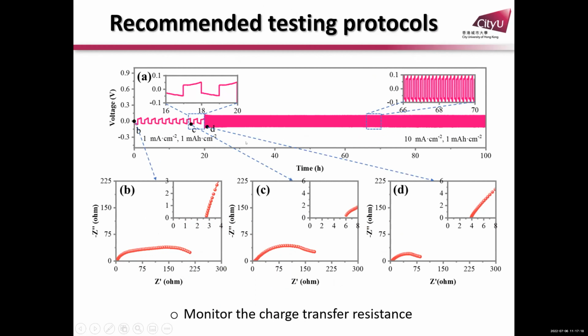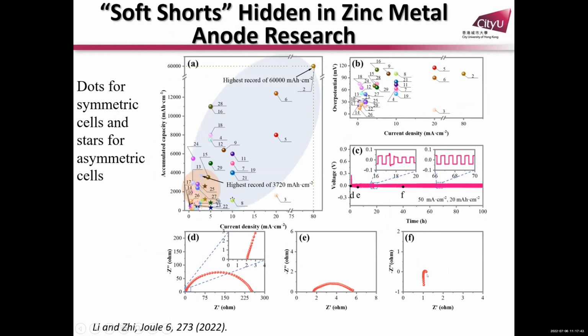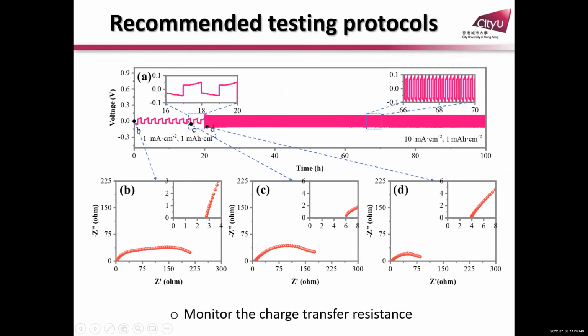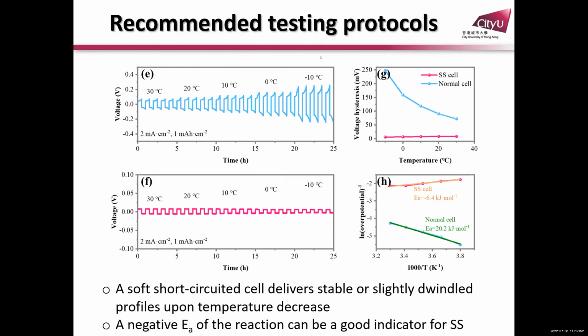So we propose a protocol to test this battery. For example, you not only test the cycling stability, but also choose a few points to test the impedance. If the impedance doesn't change that much, although it changes with different current density, generally it should be okay. If it decreases like this, that means your battery is being broken by short circuits. This is one suggested protocol. Another one: if you do the cycling stability at different temperatures, you should go to lower temperature instead of increased temperature, because of soft shorts.